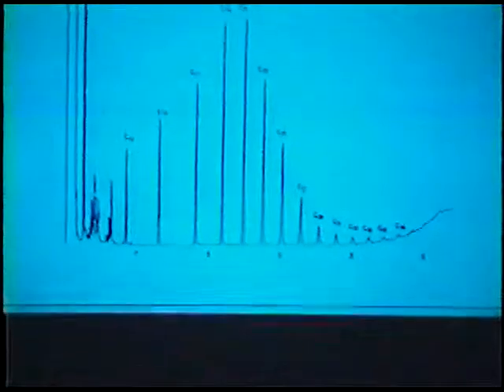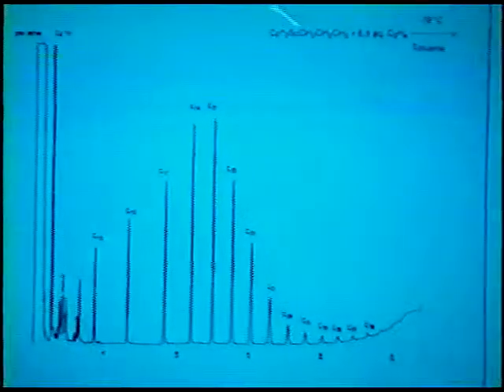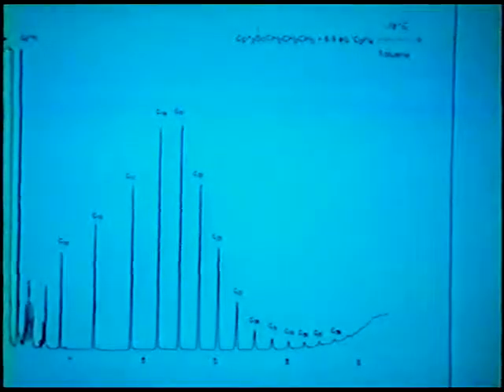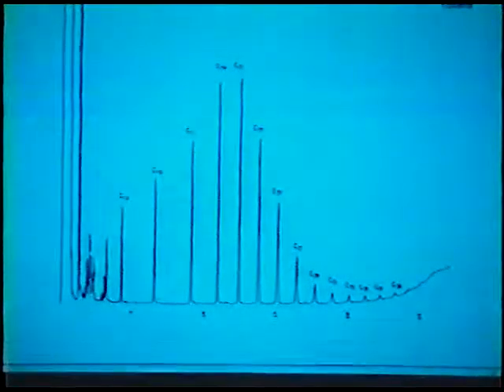With these kinds of rate constants in hand, one should be able to predict molecular weight distributions for oligoethylene. Although I'm sure you can't see up here, it says for methylscandocene propyl plus 6.9 equivalents of ethylene at dry ice temperature, where we have effectively no beta hydrogen elimination occurring, only olefin insertion. And we can assume that the ethylene insertion into the propyl is the same as into the pentyl and so forth. So chain initiation is the same as propagation, and so we should in fact have a living ethylene polymerization system under these conditions. By quenching the alkyl products with methanol and examining the oligoethylenes by GC analysis, we see here in this fraction, which is roughly C13 through C39, there are two things of note here.